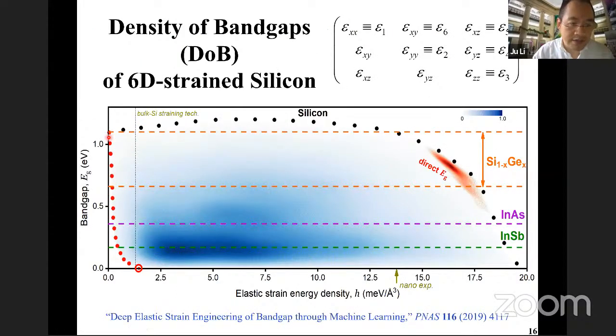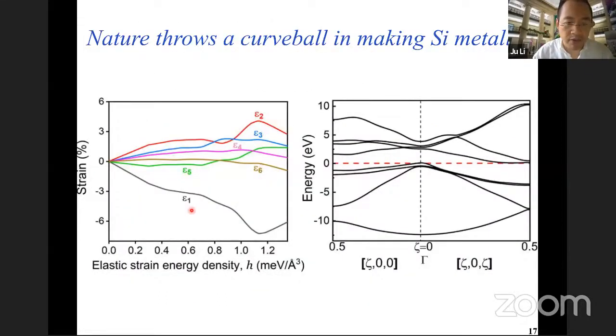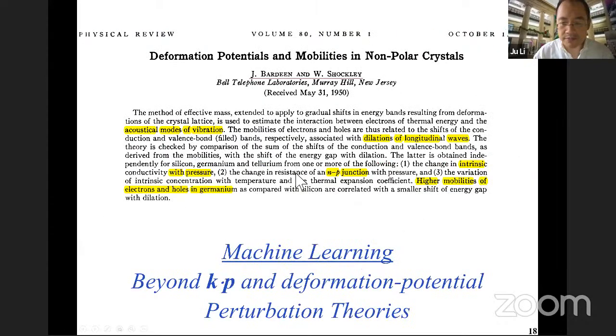However, if we trace this sort of steepest descent in strain energy for the band gap, when we look at the 6 strain components, it's actually not a straight path. And so actually nature throws a curveball, in sort of baseball language, in this 6-dimensional strain space. And so if you do linear response theory, you get these initial directions, but you will not be able to predict this kind of first metal of silicon accurately. So this is one use of machine learning in strain engineering, that you see these nonlinear behaviors.